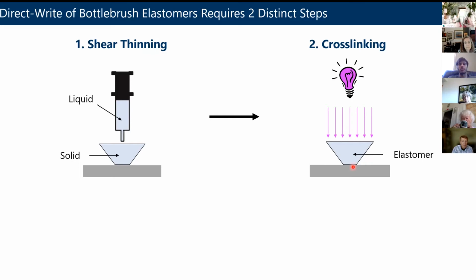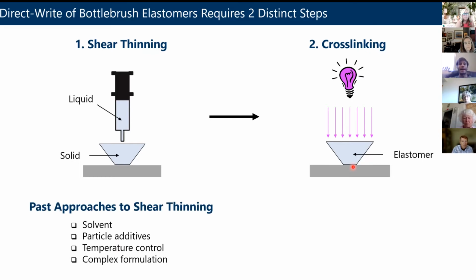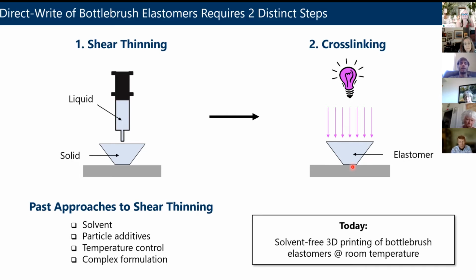And we're going to do this to make really soft elastomers that you can control the shape of using this type of 3D printing. Now, past approaches to shear thinning, again, they're not straightforward. They can be complicated to optimize. We're not going to worry about those so much. We're going to try to design easier routes to get this. And we like a solvent-free process. You don't have to worry about organic solvents, removing them, shrinkage of the structure as they evaporate. And we're going to try to do this at room temperature so you don't have to worry about heating up the syringe, cooling it down, controlling the temperature in any way.